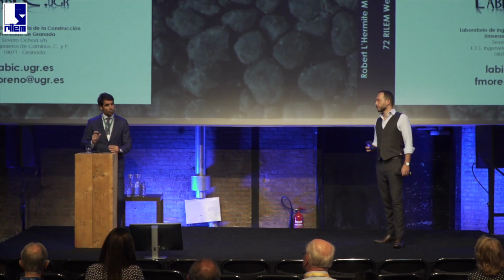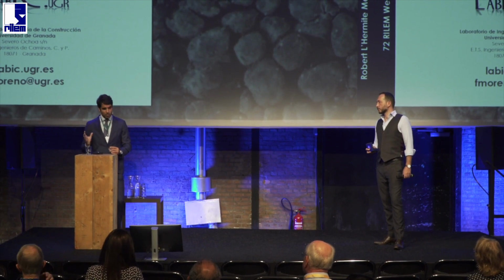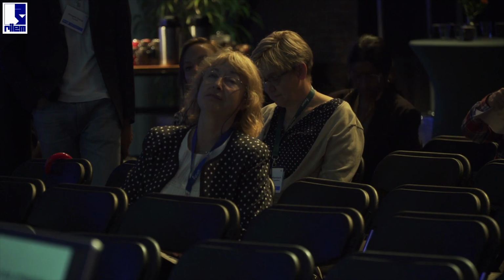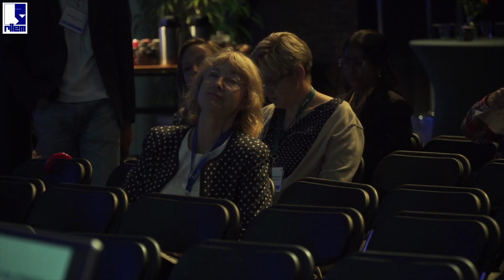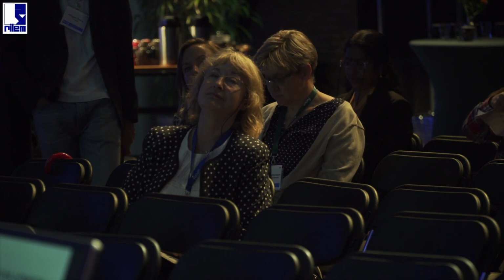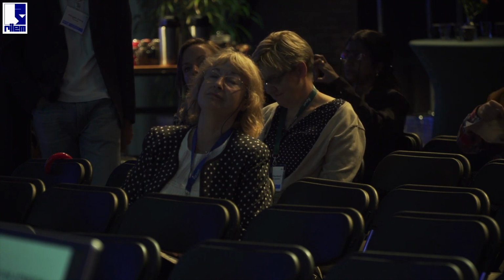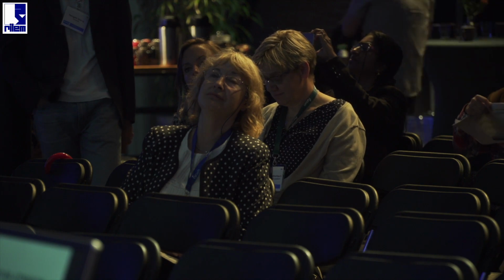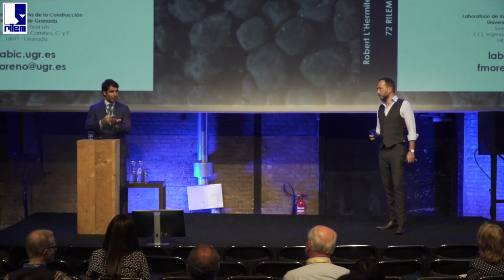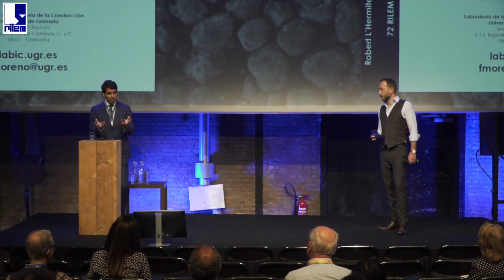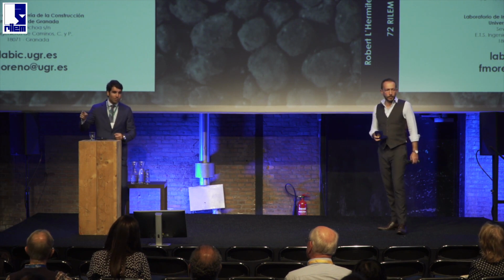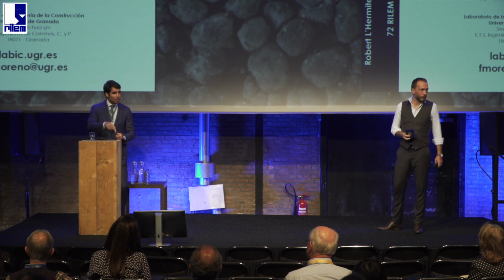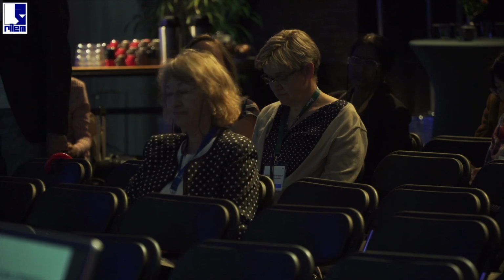And we use that to define our mean damage parameter. That was one of the advantages of that damage parameter, which integrates time, number of load repetitions, and change in the viscoelastic response, because we control the increment of the dissipated energy of the loading. So with just one parameter, if it is high, your material is susceptible to cracking, and if it is low, the material will resist.